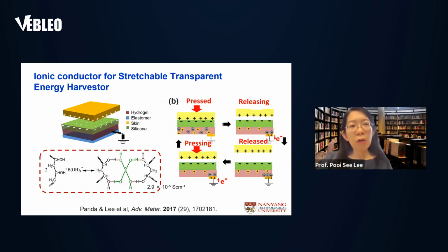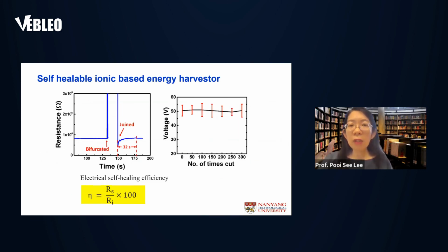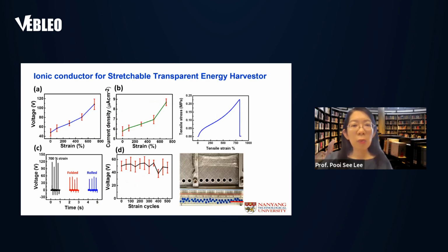And for the use of ionic conductor in the transparent energy harvester, we have employed first hydrogel, which has abundant water that creates this network that is highly transparent and also contains a lot of ionic species. And it is a very good self-recoverable material as well, with the ionic base, the material that has a high self-healability. And we can see here the transparent energy harvester is almost like a transparent skin, and then it can harvest energy through the mechanical motion, and it is highly stretchable.